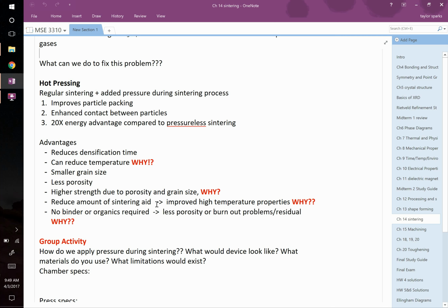We know Ostwald ripening, that's the process whereby small grains get swallowed up and turned into larger grains. That's a time-dependent process, right? Obviously, the higher the temperature, the faster it'll go, but the longer you leave it there, the more it's going to coarsen. And if you cut down time, which we know we can by doing this, then your likelihood of having small grains is better. It's a better way to make small grain ceramics, right?